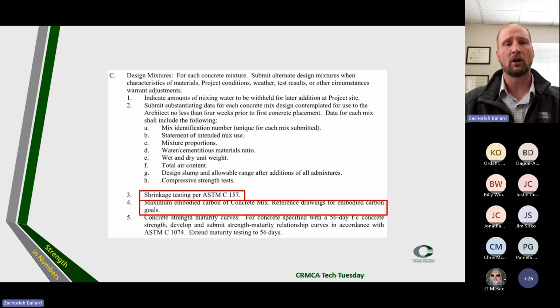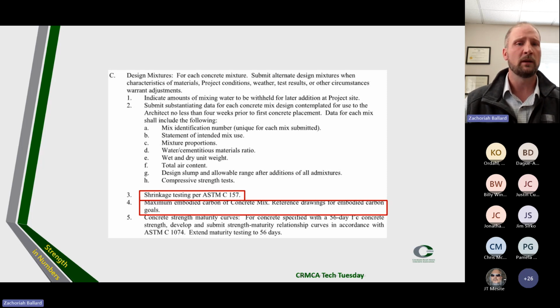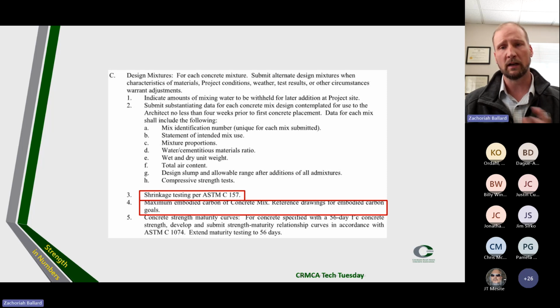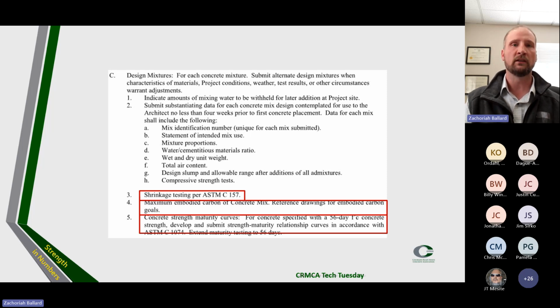We also have a maximum embodied carbon of the concrete mix, with reference drawings for embodied carbon goals. We're not going to get into that part of it, but this is another opportunity for performance engineering mixes. And our strength maturity curves: for concrete mixes specified with a 56-day strength design, develop and submit these strength maturity relationships in accordance with ASTM C1074, and extend this maturity testing out to 56 days. So not every supplier has all of these things sitting on the shelf ready to go, but if we have a handful of performance mixes, getting these types of specifications might be a little bit easier.